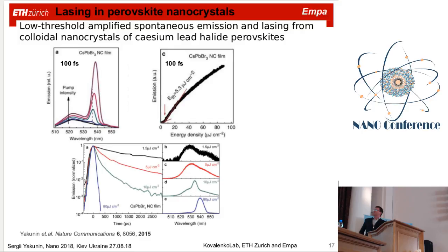For us it was, of course, a very big challenge to get it. It took us a couple of months before we understood that in order to get such an amplified spontaneous emission effect, we really need to make very compact films of nanocrystals. Afterwards, we understood that one of the critical conditions for optical gain is that nanocrystals should provide coupling of their excitons. So we believe these lasing effects and optical gain appear due to biexcitonic, or, as other people call it, bimolecular recombination and emission.